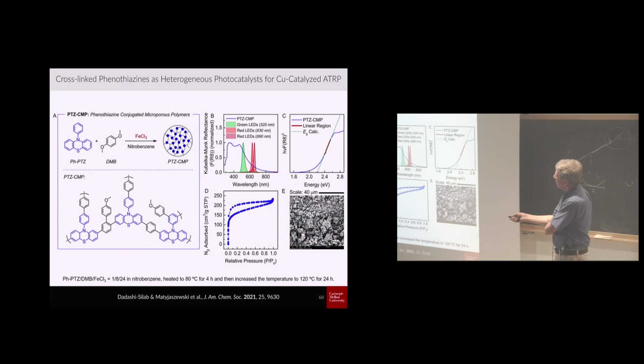So how is it done? We start with this phenothiazine, which is very inexpensive. It costs probably $10 a kilo nearly, because it's used for something else. And when you start with dimethoxybenzene, in the presence of iron trichloride, which acts as a Lewis acid, you have a Friedel-Crafts reaction, and you get a mess. You get an insoluble system.